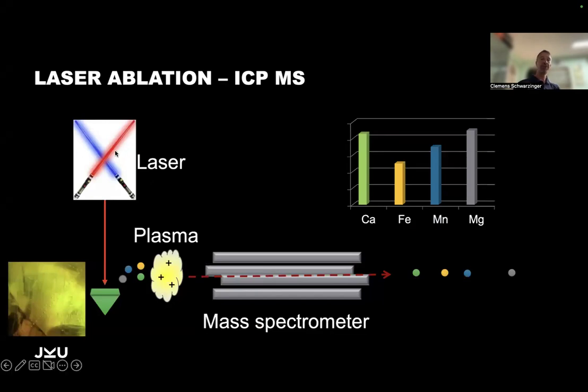So here's a little bit more traditional plot of what we have. We have the laser swords from Star Wars, of course, and we shoot at the surface of our gemstones. You see here, if you look careful, there are 2 lines of small points running from bottom left to top right. And these are all the points where we have shot with the laser onto the gemstone and then sent them with a gas stream into the plasma where we ionize them. And then we have a mass spectrometer. The mass spectrometer is the analytical tool of choice for any chemist because it can tell you almost everything at a very high resolution and a very high separation efficiency.